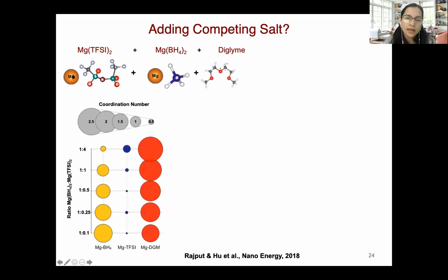And here we added magnesium TFSI with magnesium borohydride salt in a Diglyme solvent. And the purpose was to let these 2 anions compete with each other to bind with magnesium. So computationally, we screened a series of different ratios of these 2 salts to find the ratio where neither of these salts are forming contact ion pairs, and the coordination number of both magnesium borohydride as well as TFSI is on average less than 1.